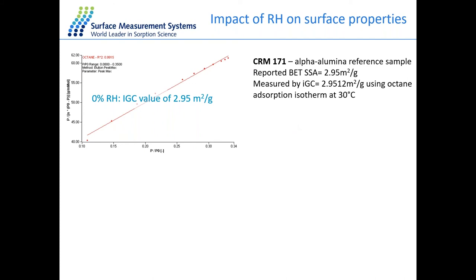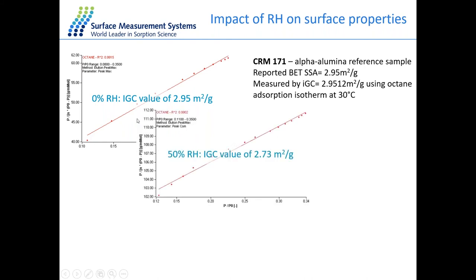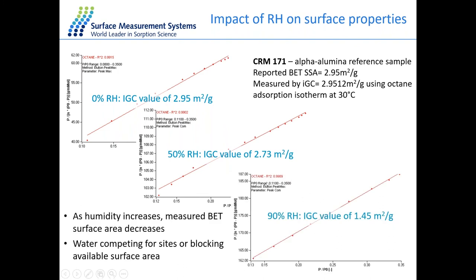As I mentioned, we can also equip a background humidity controller inside the system, which means we can study the impact of humidity on the surface property. For example, here the sample is the alpha alumina 171 sample. The surface area at dry condition is reported as 2.95 square meter per gram. Then we performed the same experiment at different humidity. As you can see, at 90% RH, the surface area of this sample is only 1.5 square meter per gram. It drops to half of the value at dry condition, because the water molecules compete for the sites on the surface and also block the surface from the organic vapors.